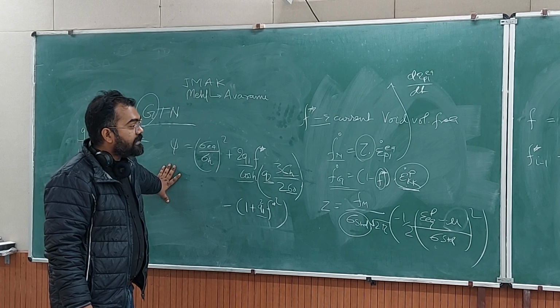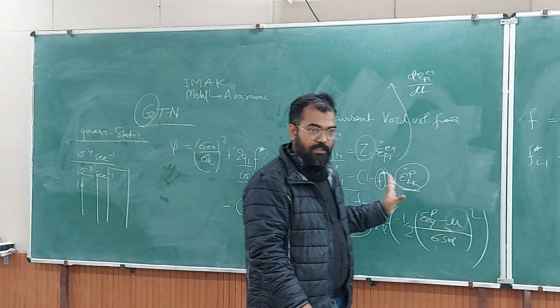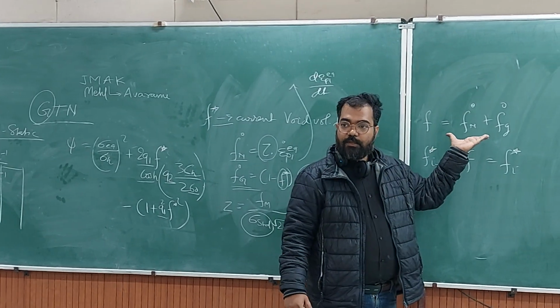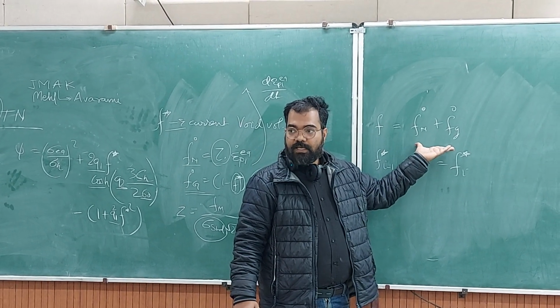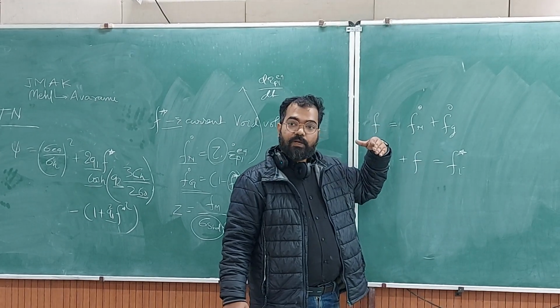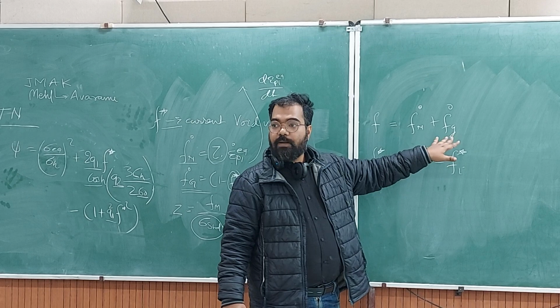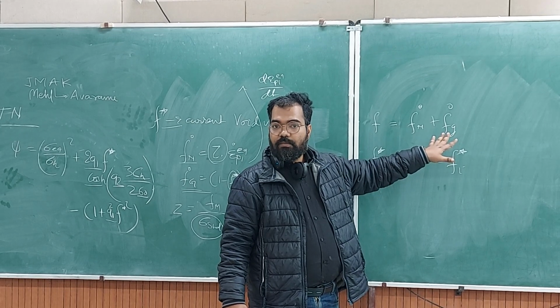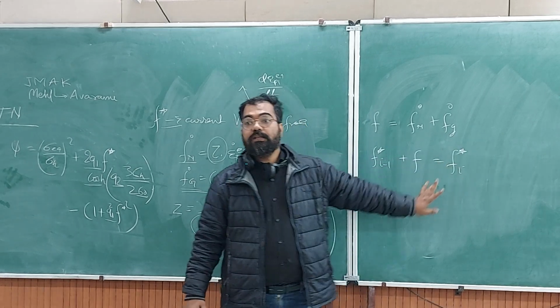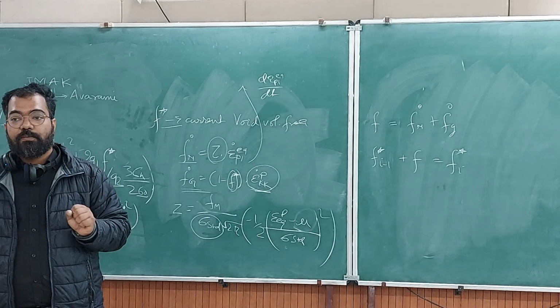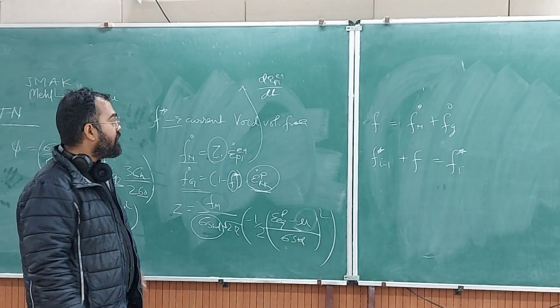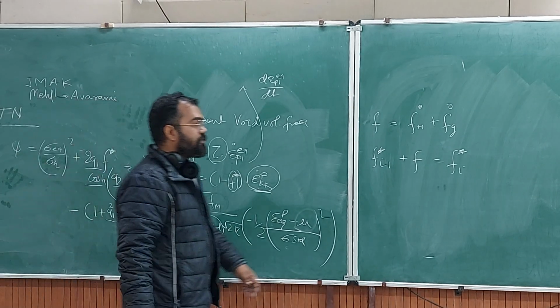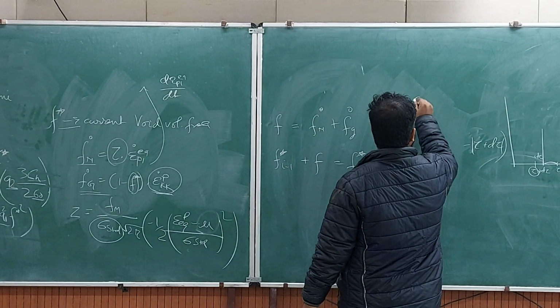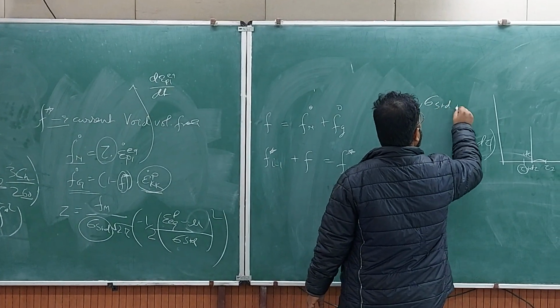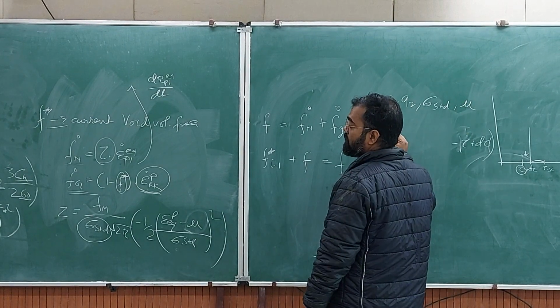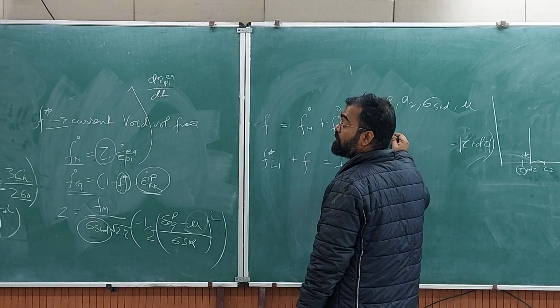What is happening wrong here, in my opinion, is that you can't simply add nucleation rate and growth. That's why I explained Avrami first. Because this would mean that while growth is happening, nucleation is not happening. But this model really shows a good correlation with the experiments. Although there is another problem. To simulate damage using this model, you need to know Q1, Q2, sigma, standard deviation, mean, what else? That's it.